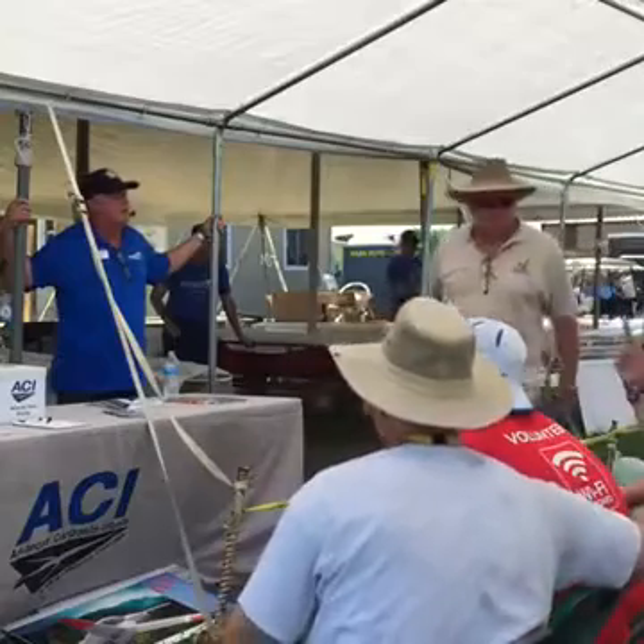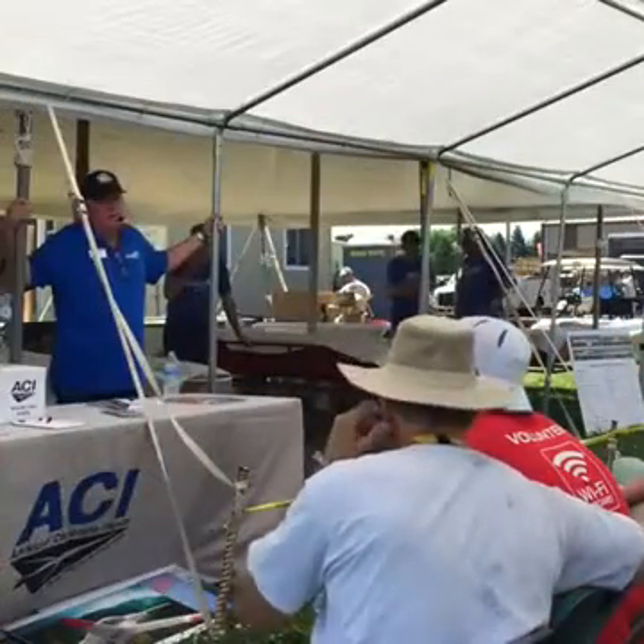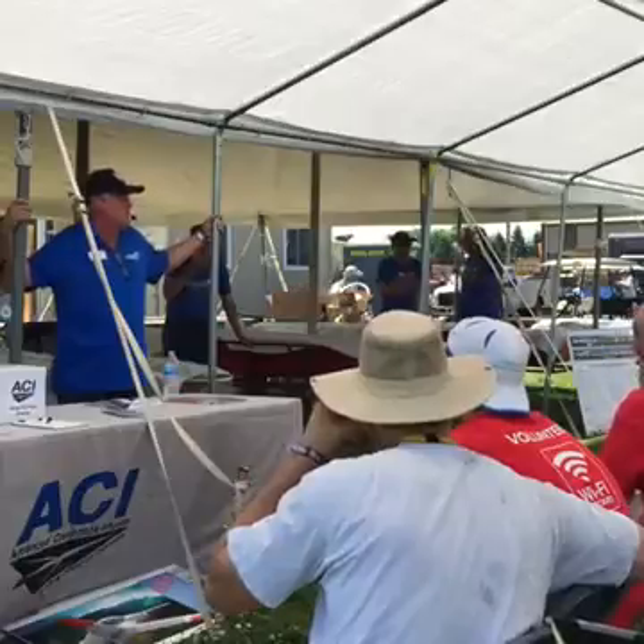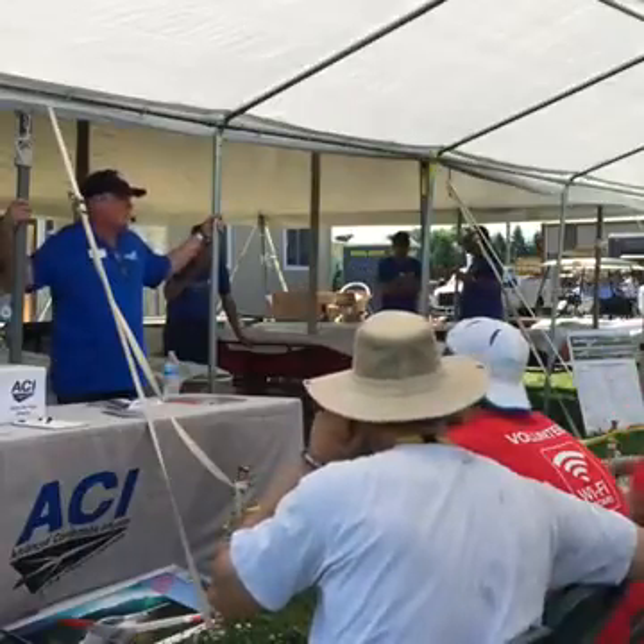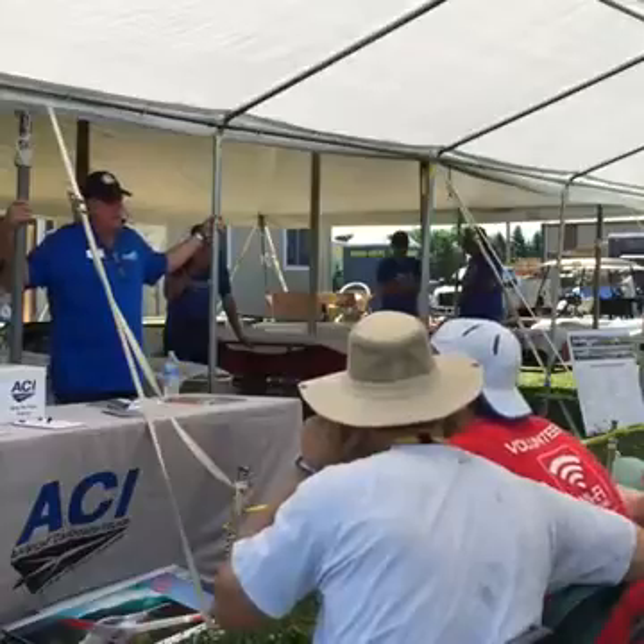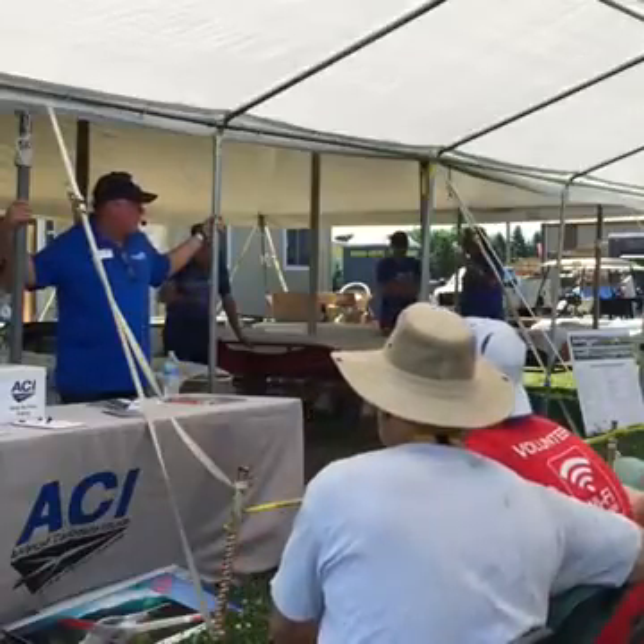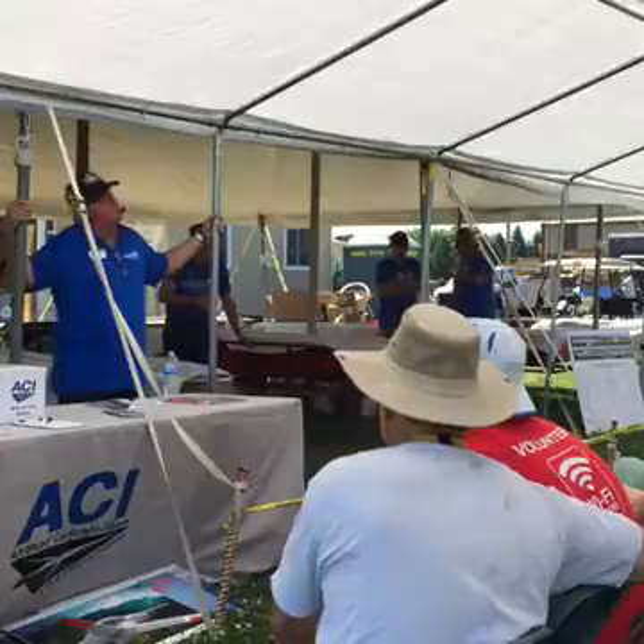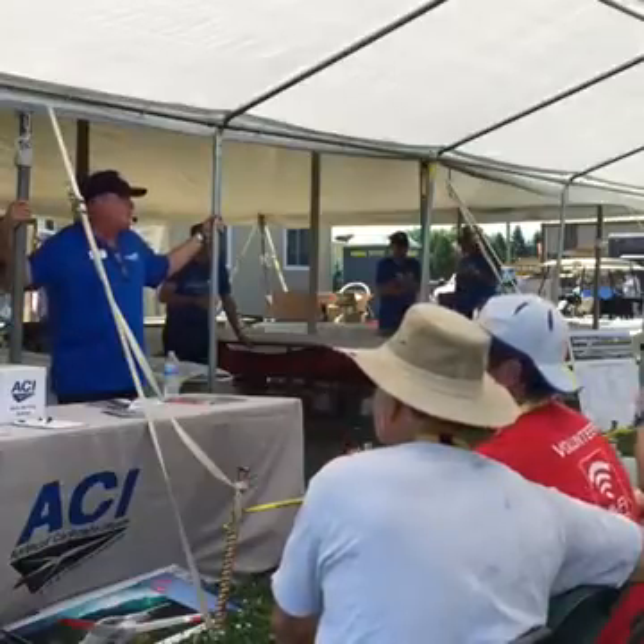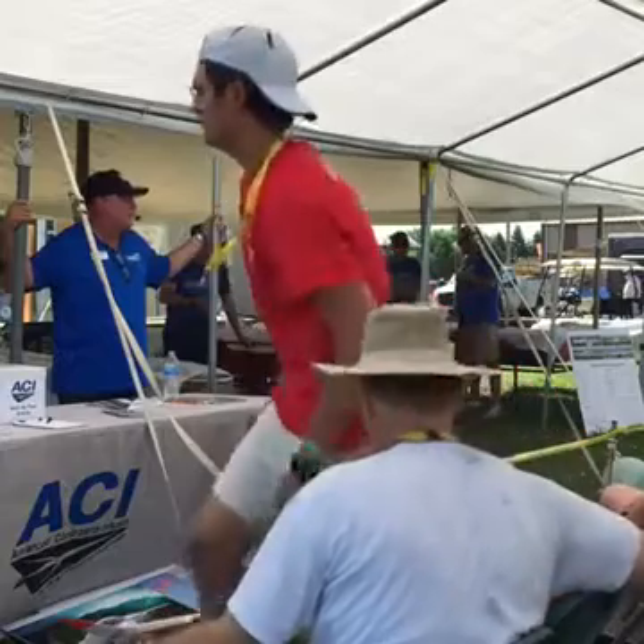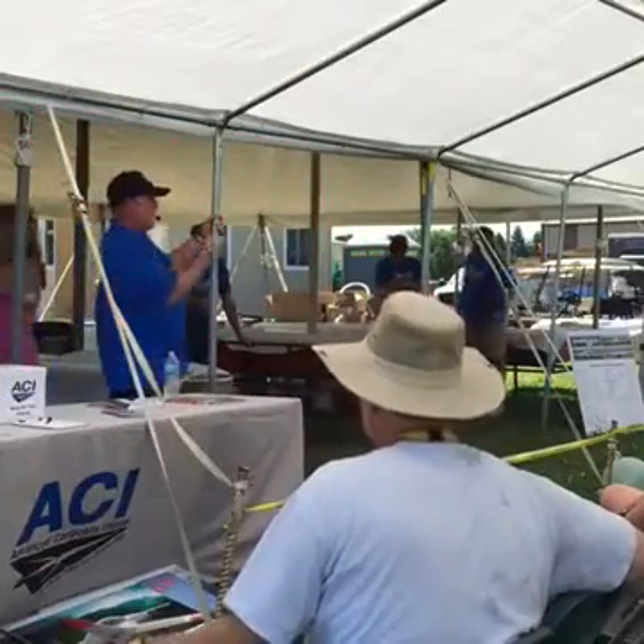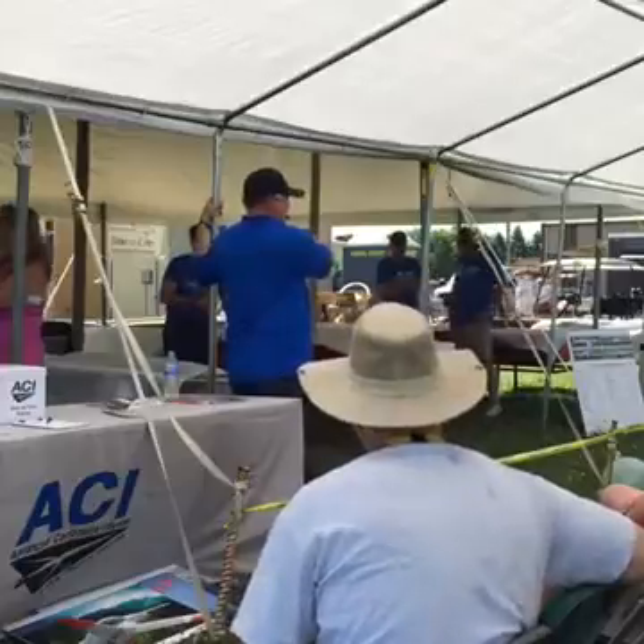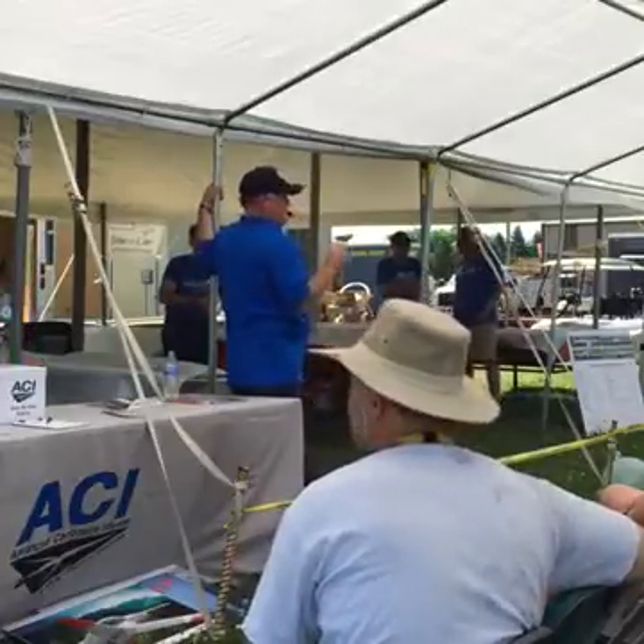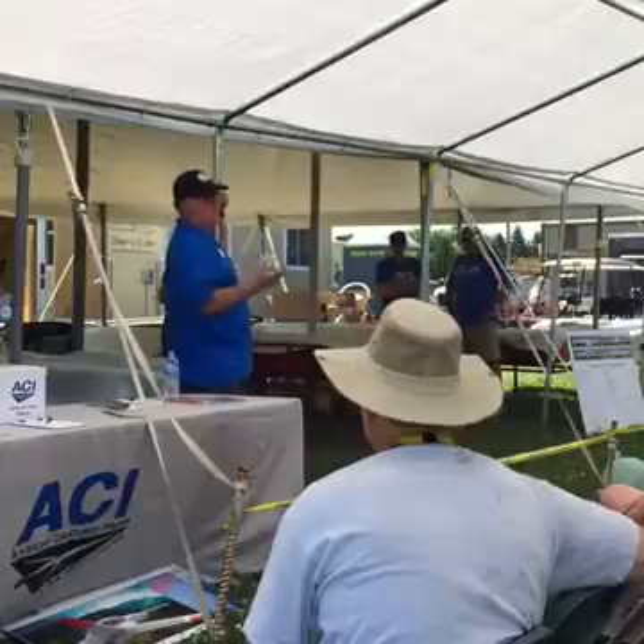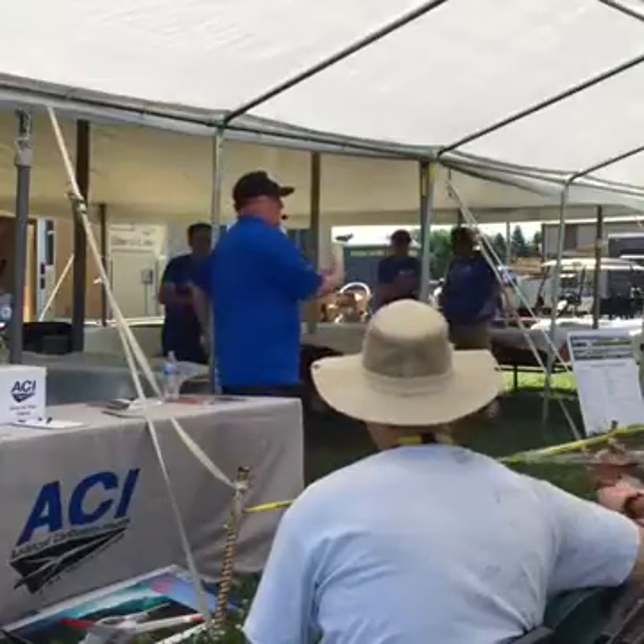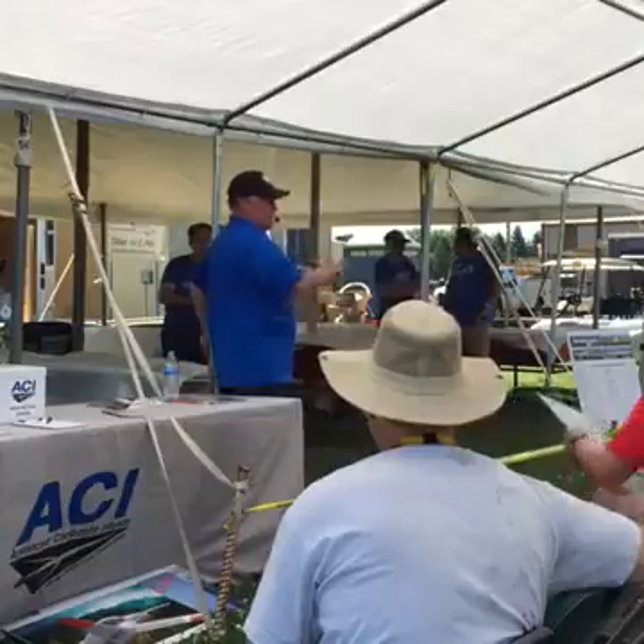We're using some tackifier here to help hold the fabrics in place in the tool. For the purposes of this demonstration and the resin systems I'm using, we're using just a 3M Super 77 spray tack. You want to be sparing with it and only use what's necessary to keep your fabric where you want it to be, because anything that you add to a laminate stack is FOD, foreign object debris, and you want to try to minimize that. On the resin system that we're using on these two parts over here, the Super 77 will 100% become part of the resin system.